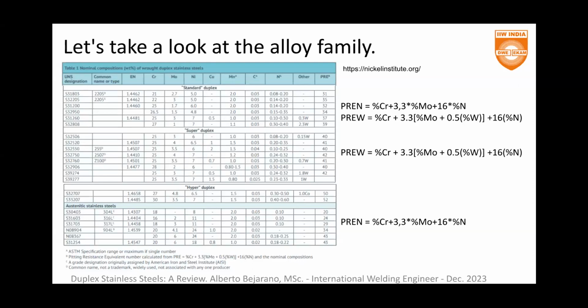a very important consideration in terms of money: the quantity of nickel in 316L is 11, but hyper duplex only has from 6.5 to 7% of nickel. In fact, the promotion of this kind of stainless steel was done because of the crisis of nickel. The price of nickel had a rise pretty difficult for the steel makers to follow. So they started working again with this family of alloys, and it was a total success.